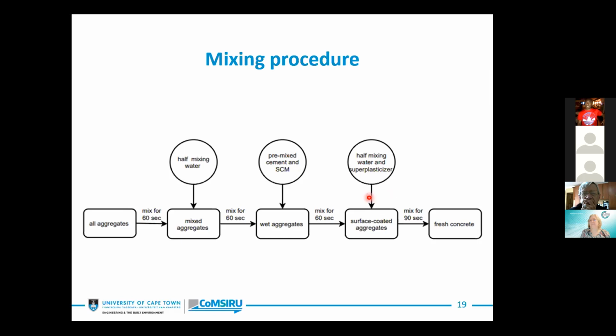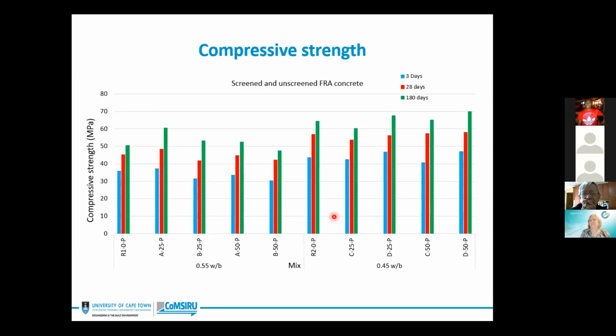And for our mixes, we have also used superplasticizers to achieve our design workability, which was fixed at 75 plus or minus 25 millimeters. The SP dosage is kept at minimum to limit any influence of SP. Also, no additional water or water reduction was carried out during this mixing. So here, just a quick look at some of our results. Here's the compressive strength result.